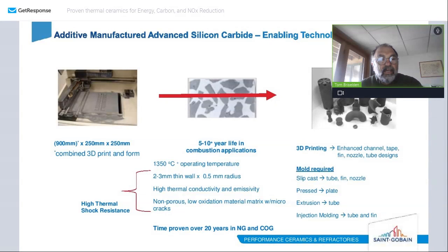In order to achieve the energy, carbon, and NOx reduction goals, the material plays a critical role in allowing these designs to operate effectively in extreme environments, namely high temperature to meet all applications, thin walls, high thermal conductivity and emissivity for excellent heat transfer. A non-porous, low oxidation material matrix is required. When we combine these components, they significantly reduce thermal shock, resulting in really a perfect material for long life in combustion environments, using both natural gas and coke oven gas.